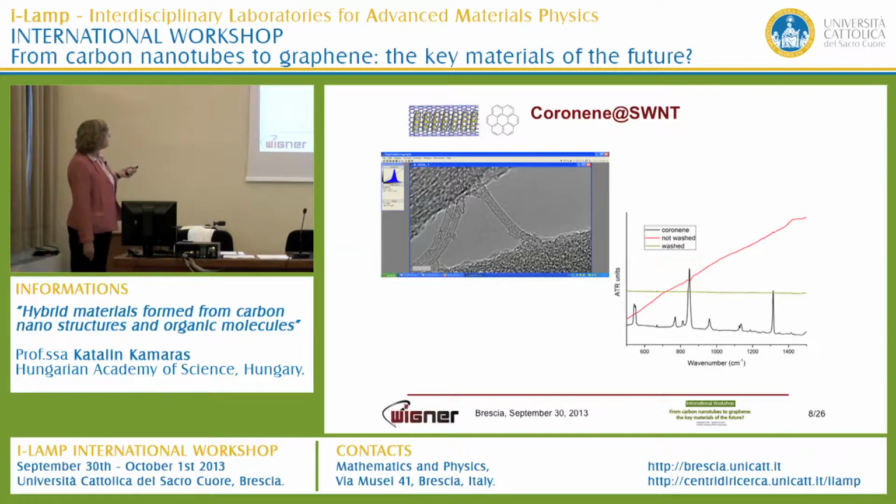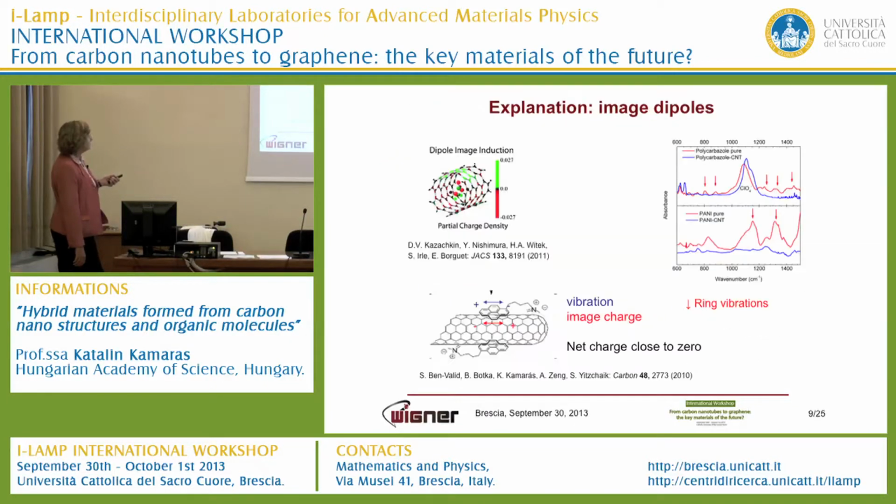The explanation is that as soon as you have a dipole vibration here, you have an image dipole in the wall of the nanotube from the delocalized electrons, and your image charge will move out of phase with your vibration and will cancel the vibration. That's a very nice explanation, and I think we have it all.